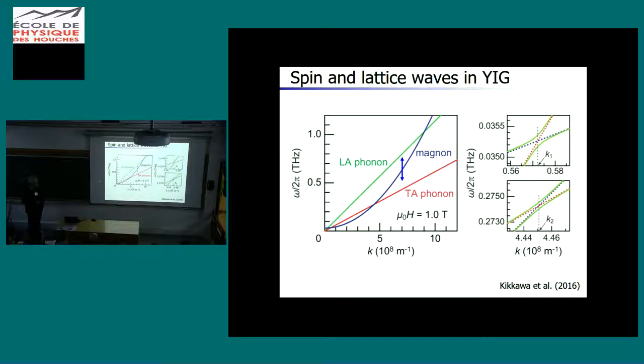Now this can be easily calculated for YIG parameters here. You see that we have a parabolic magnon dispersion here. There are the TA and the LA phonons. The magnon dispersion can be shifted up and down with the magnetic field relative to the phonons. Now, if you look closely at these crossings here, you see the effect of the magnetoelastic coupling, which is actually pretty small in YIG. So this is basically the basics of spin mechanics.